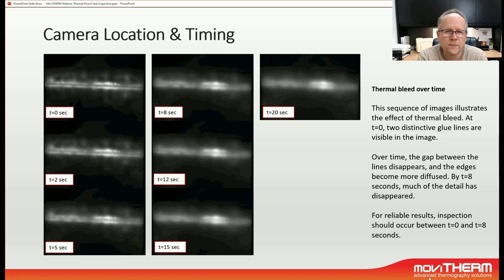For that, what we have done is seal a bag and take a video of the bag seal cooling down. So we have just placed a sealed bag onto the conveyor at the exact working distance that we had determined before, right about where the proximity sensor was, and just left the bag there standing still while we were recording a thermal video. And the outcome of this test are these image sequences, and we have extracted certain points in time.